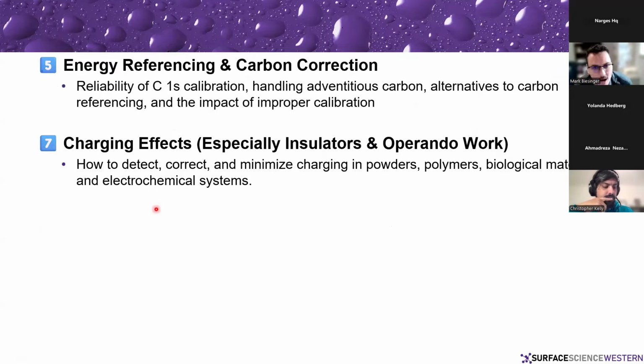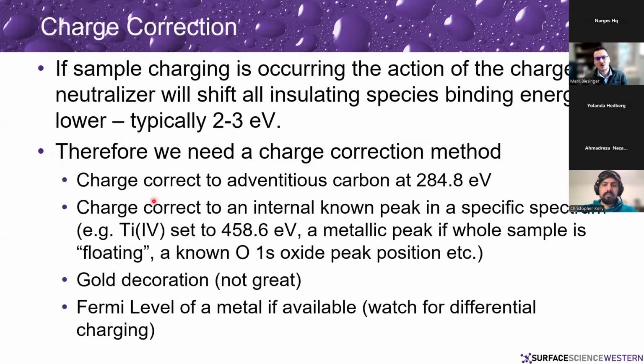Energy referencing and carbon correction. This is a pet project of mine, and charging effects. So, charge correction. We talked about a little of this before. If a sample is charging or it's insulating, the action of the charge neutralizer will shift all species down, 2 to 3 eV is generally what we see. And so therefore we need to have a charge correction method so that we can have an energy reference so we know what we're looking at.